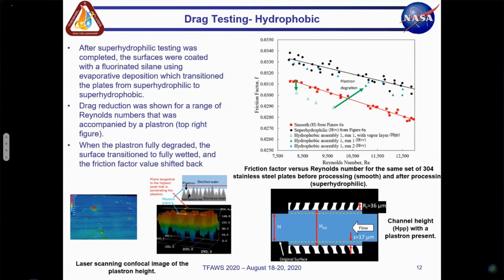from the open green triangles to the closed green triangles. And then we go back through and run the test again without changing anything in the setup itself. Now we see that the second run itself falls slightly below the superhydrophilic. So that would show what I talked about in the background, where you still have a hydrophobic surface, though that plastron and air layer is gone, you're still getting a small slip length. So that's why the data for the hydrophobic surface falls below the superhydrophilic.